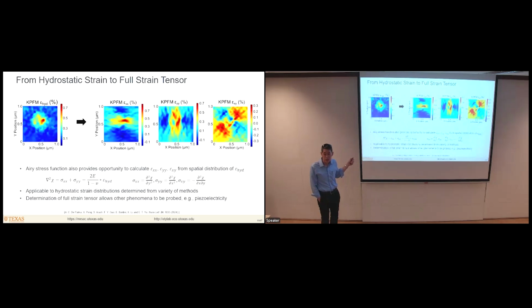Okay, so to analyze piezoelectricity in these materials, what we first need to do is to go from just the hydrostatic strain to the full strain tensor. And we can again get that from this thin plate deflection analysis. It turns out that the hydrostatic strain can be used in this expression here to again get the Airy stress function. And then from that, you're able to get the stress and then the strain tensors. Once we have the full strain tensor, then we can see what that predicts about the presence and the nature of piezoelectricity in these materials.